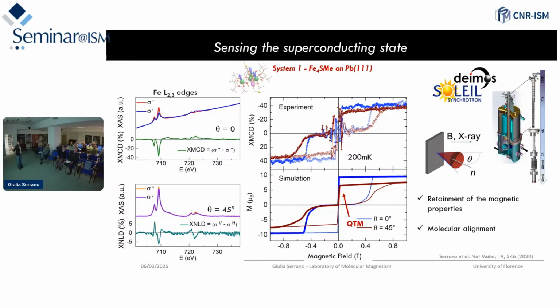If you see the blue curve, this is the hysteresis loop that we record when we impinge normally with the X-ray and the magnetic field on the surface. We also simulated this curve, taking the proper Hamiltonian approach for this system, and we see that the system is actually characterized by a large hysteresis loop and by these two characteristic jumps that correspond to the resonant quantum tunneling of the magnetization that I mentioned before. This is very important because then we expect that the molecule behaves as it should in bulk, where as soon as it feels zero field, it starts to lose its magnetization, starts to resonantly tunnel between the up and down state.